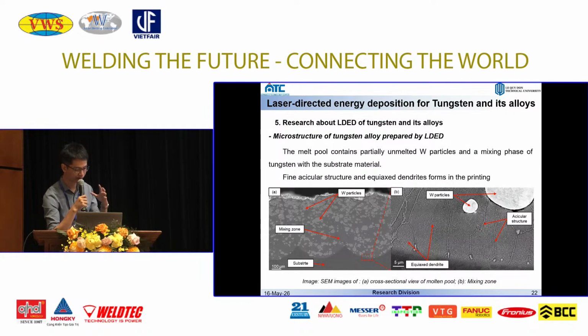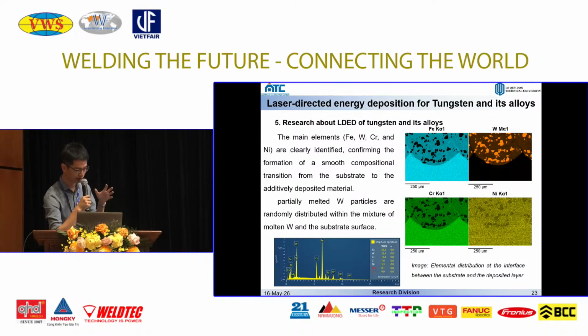And we also use the SEM to see the microstructure inside the deposited layer. In the image here, we have the substrate zone, the mixing zone, and the partially melted tungsten particles. This image shows the EDS spectrum and elemental mapping in the mixing zone between the substrate and the powder after scanning, so we can clearly see elements like iron, tungsten, chromium, and nickel. These are the main elements inside the composite material here.